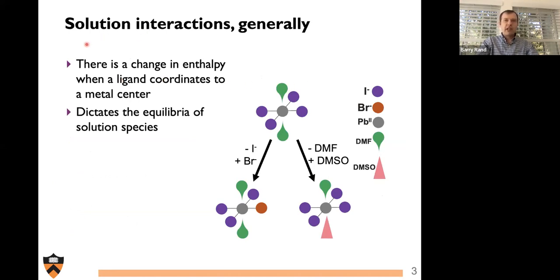So in general, we can think about having lead iodide hanging around in solution. And when you change the stoichiometry or composition of the solution, there are numerous options that can result due to equilibria of various solution species that might be around. For example, if you had lead iodide coordinated by DMF, but introduced bromide into that ink, it could be that bromide takes the place of an iodide, or introduce DMSO to that ink, and it could be that DMSO quite likely will take the place of a DMF, which had equilibrated with the lead iodide hanging around in solution.